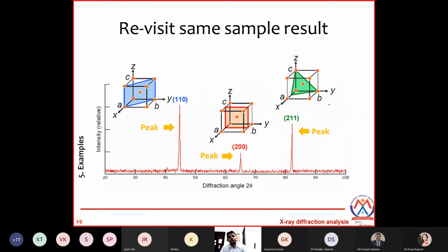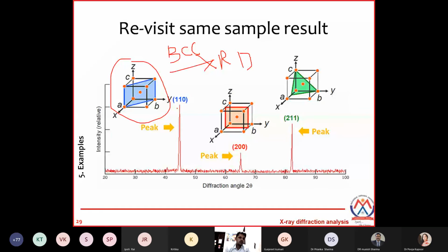Let us revisit the sample results we saw in the starting. Just understand, this is an actual XRD peak. You can see the material I have deliberately chosen is BCC. This is a BCC structure. In a BCC structure, we don't have any peak for 100. This we call a systematic absence. Okay, but the second order we got. This is a second order peak.